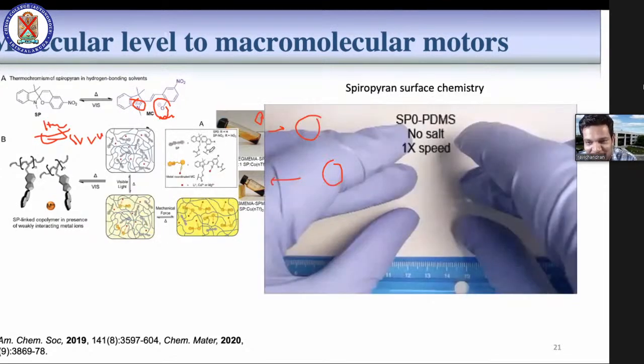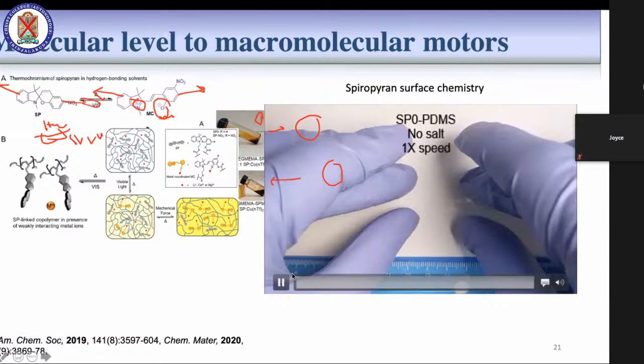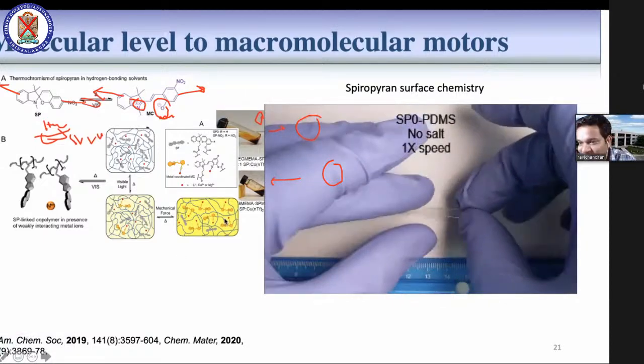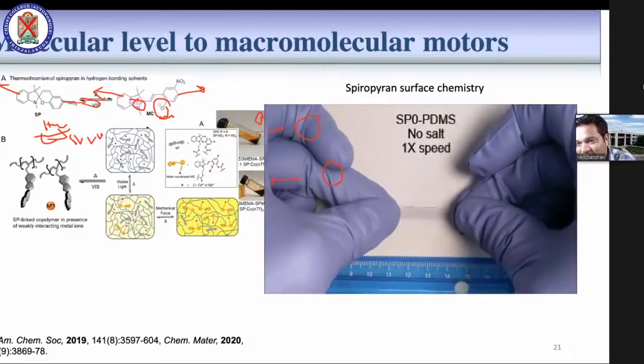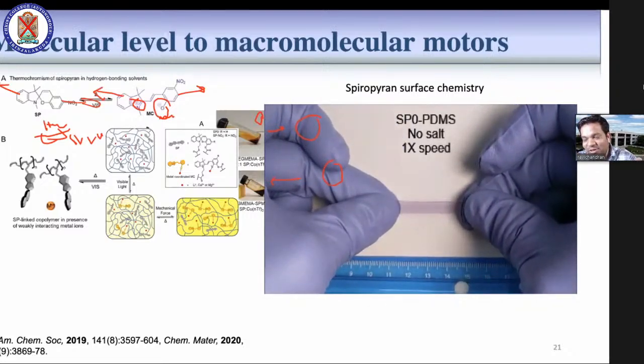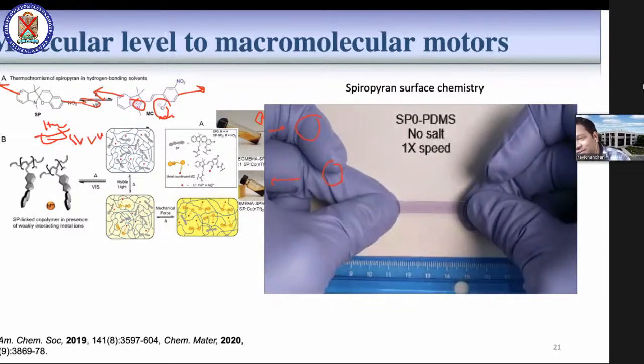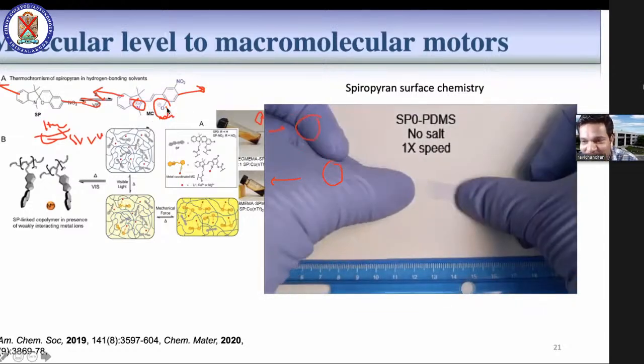You can also create mechanophores and apply force on both sides. This ring can open and form the merocyanine structure. For this, you can do simple addition chemistry with silane chemistry, and apply the force with PDMS spiropyran, which is cross-linked with the silane. When you stretch, applying the force, it goes from colorless to a purple color, which is the ring-opened structure of the spiro, which is merocyanine.